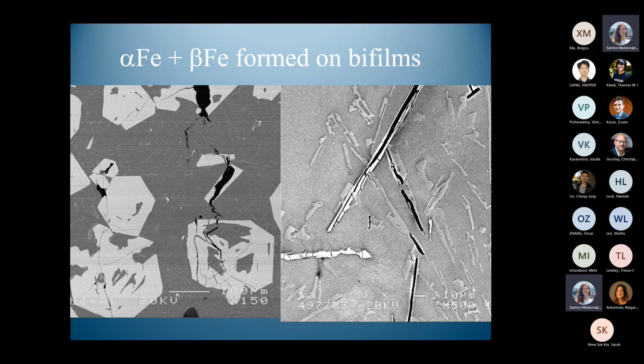And that contrasts with this situation, where now we've got alpha iron particles. The alpha iron is a very nice cubic lattice. And because it's a cubic lattice, it can grow in any direction it wants. It's not constrained to grow as a long platelet. It can grow in a compact crystal if it wishes. And so, back to our convoluted bifilm as it is when it starts in the liquid. And now the alpha particle nucleates on it. And now the alpha particle can actually grow around this corner and that corner and that corner and that one. And so it wraps around this particle and freezes it in place so it can't open.